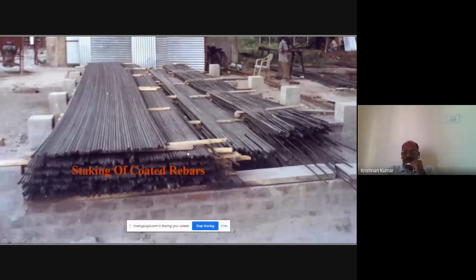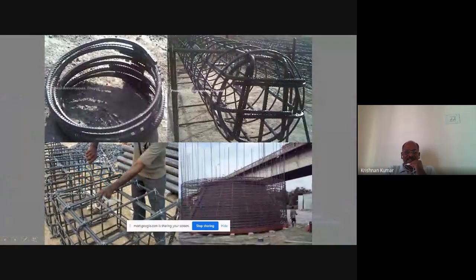We have to make the stacking like this because abrasion should not happen on the coated reinforcement. So we have wooden planks like this, over which we stack the coated rods. This rod can be bent and utilized for construction. You see that this rod can be bent to any shape, as it has its own flexibility. It will not have any crack on these edges. Even if any damage happens, the primer and sealing coat are both liquid, so we can touch up here, and both have the same property.